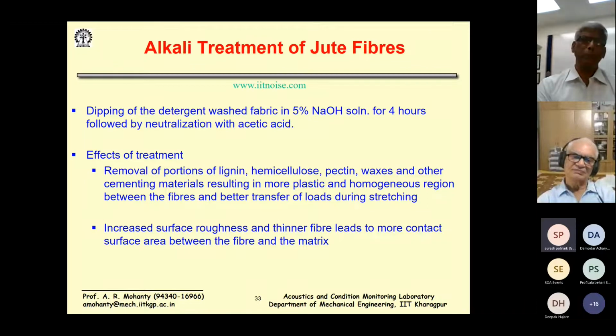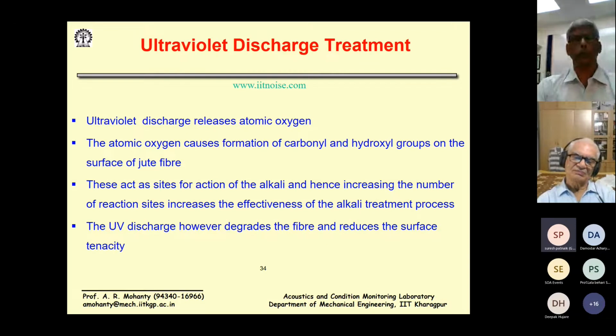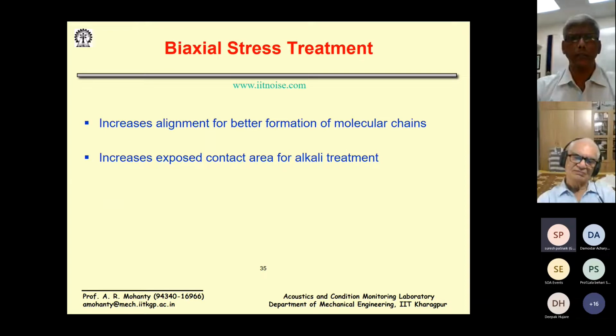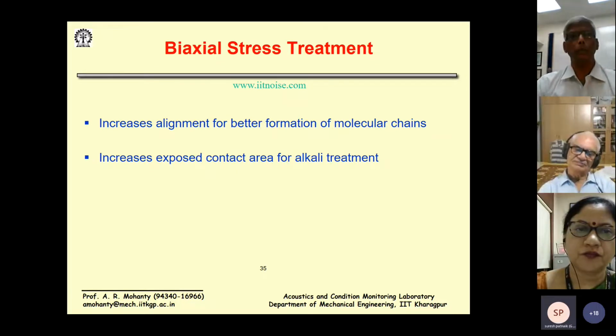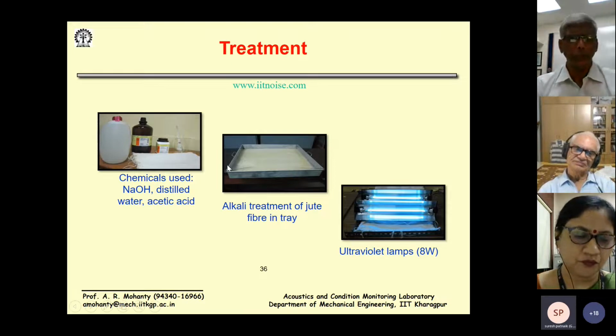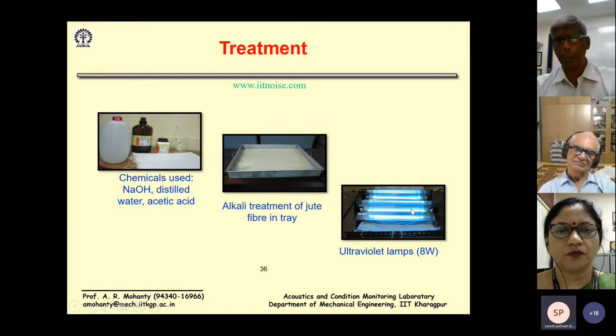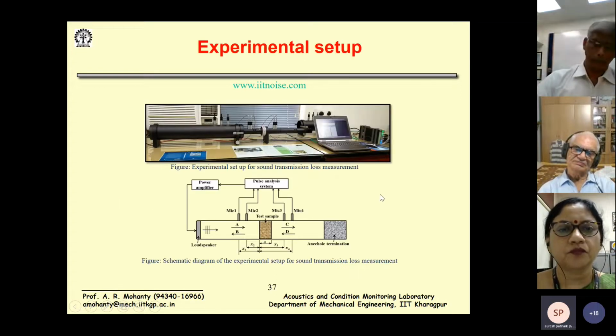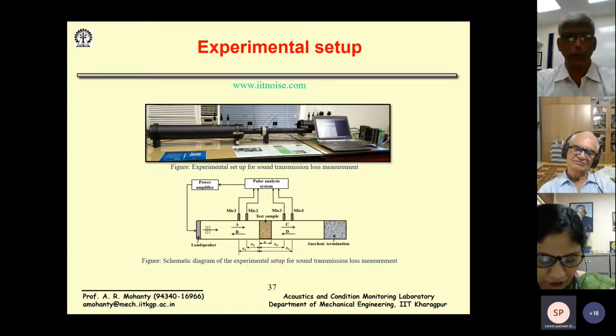So if this recipe is given to any jute manufacturer, and I have given it to many industries, which they are using now to develop materials out of jute, which can be good composite boards or good absorbers. Of course, I will not go into details of this ultraviolet discharge treatment, etc. Of course, we did a biaxial stress treatment, so that there is better alignment of the molecule chains and exposed contact area for better alkali treatment. And this was all done at the lab level, and then we transferred the technology to some companies. I will come to that later on.